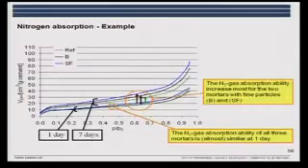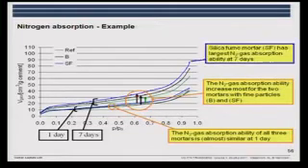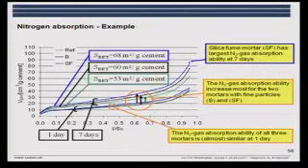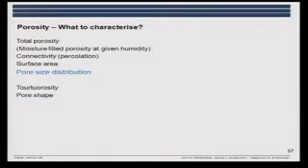But for 7 days, the paste with silica fume has a larger surface area, and the bentonite paste also has a larger surface area than the reference. So it can be used to characterize the impact of these supplementary materials on the structure of the paste. And this is what we see. And from these curves, we can determine the surface area of the materials.